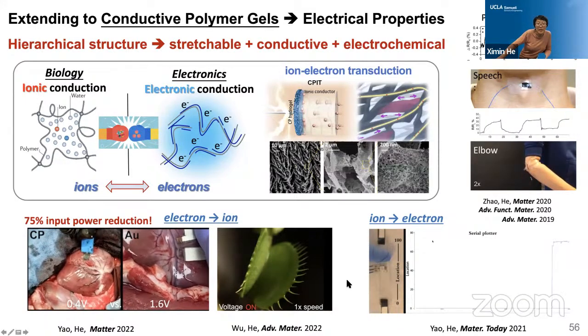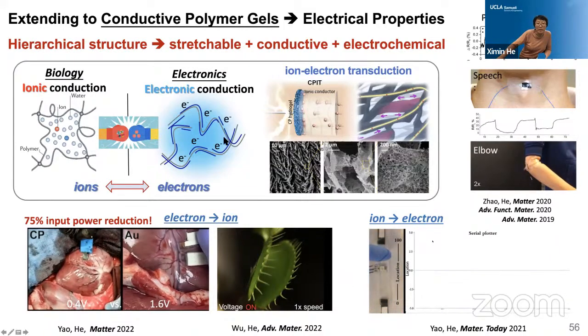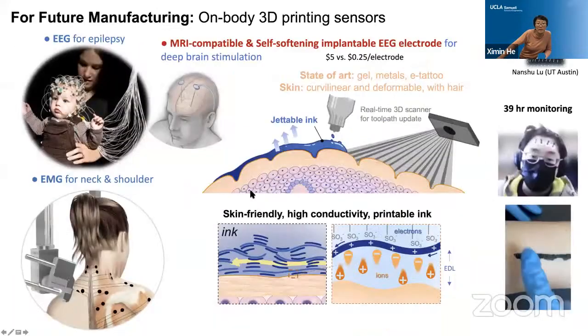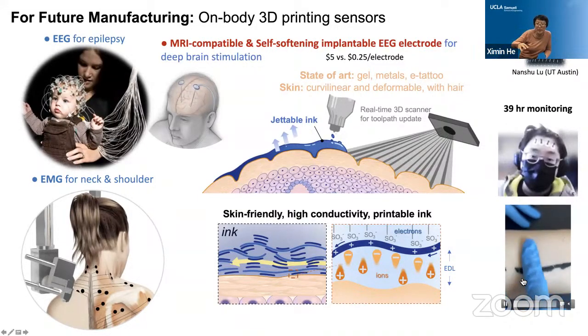And then with this, we're working with Professor Nanshu Lu at UT Austin to develop this on-skin direct printing using our conducting polymer ink, where direct on-skin printing can yield personalized biosensors that can be used for EEG or EMG. And this video shows a directly inkjet-printed conducting path that is pretty robust and sturdy, to allow the patient or the subject to wear this over a couple of days.